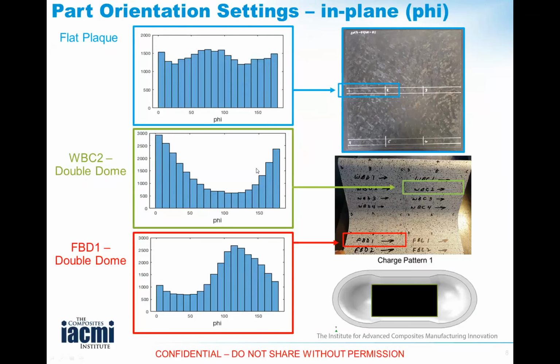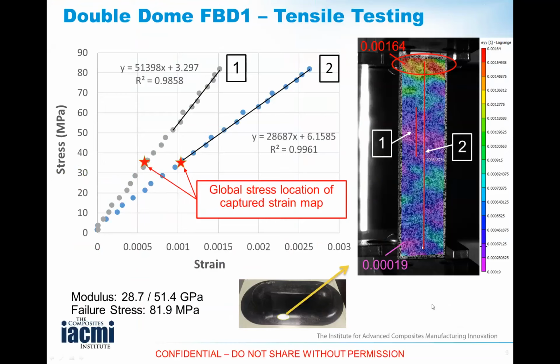But once you mold the components, you get this preferential orientation depending on where you are, and that would control your mechanical properties. The other challenge with these discontinuous fiber systems is that none of the continuous composite mechanics really applies, even for testing. Here is an example: if I take a coupon sample out of this region near the flange and the wall, and I do the tensile test, this is the stress versus strain, and I pick a point here shown in red dots, it's roughly about 35 MPa. This sample failed at about 80 MPa, so this is half of the tensile strength.